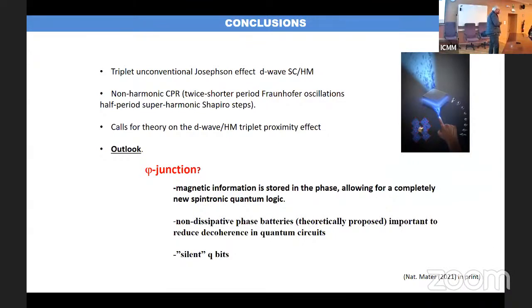Very interesting talk and results, Jacobo. So I have a question about your Fraunhofer results. You mentioned that you actually go to the dissipative state to measure the Fraunhofer patterns. So I guess the point is that you cannot really measure the switching currents in your device in an accurate manner, right? Because in principle, you could detect the zero pi transition already in the switching currents of your device, right? But apparently you cannot. So how do you relate this dissipative state to the true critical current of the junction?